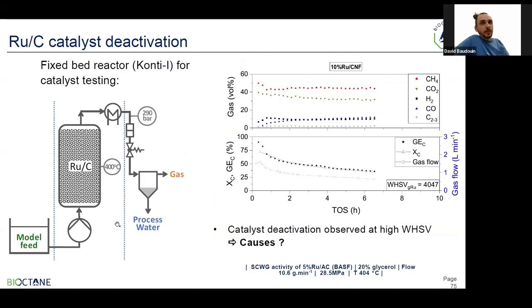So of course, this raises the question of what this is caused by. There are indications that the surface plays a role also in the deactivation, and actually the clean surface that is free of ruthenium particles might play a role in the deactivation of the catalyst. By this I mean the deposition of coke, and this is something we have further investigated. Next slide, please.